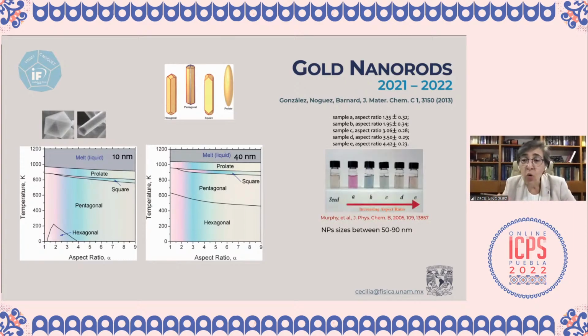And you can look at these examples also experimentally. The important feature here is that when you polarize along the nanoparticle, you have a larger length as compared with when you polarize the light along the width of the nanoparticle. These two modes are the ones that rule the optical response of the plasmonic system. And you can see exactly the same colors, like the pink, the blue, the red, and then a dirty kind of solution, a brown-like system. Okay.